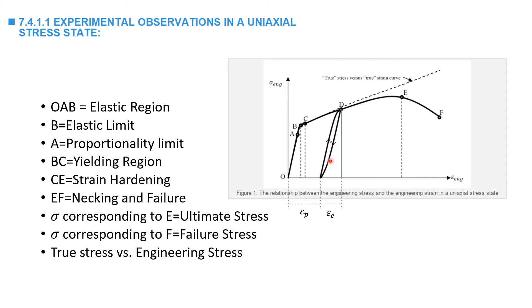Upon reloading, the material behaves elastically until reaching the same location on the curve, point D, which is considered a new yield point for the specimen. At point D, the total strain can be divided into two components: an elastic strain equal to the stress divided by Young's modulus, and a permanent plastic strain termed Epsilon P. The term hardening describes the increase in the yield point with the increase of the amount of permanent plastic strain.